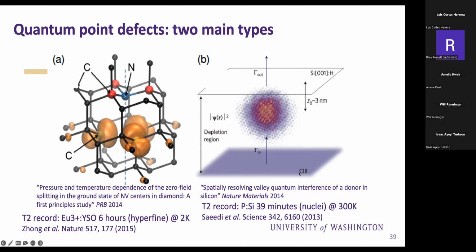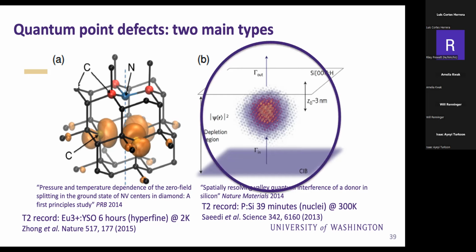This was a curious experiment where they actually initialized the nuclear spin. This was an ensemble experiment. They initialized an ensemble of nuclear spins at low temperature, increased their cryostat up to room temperature, then cooled it back down, and then read out the state to show that they could get a 39-minute coherence time at 300 Kelvin, actually at room temperature. So both systems can be highly coherent if you have the right host-defect combination.